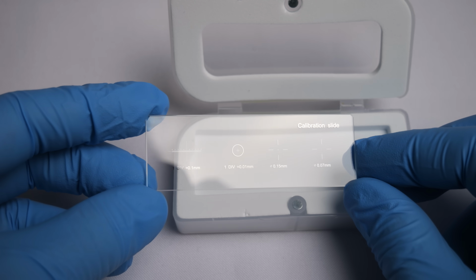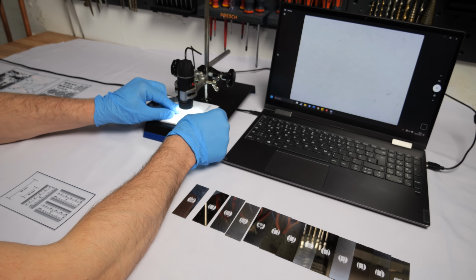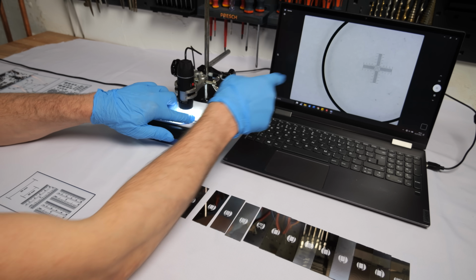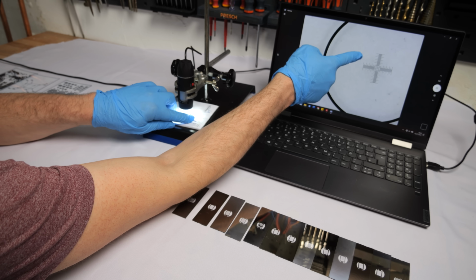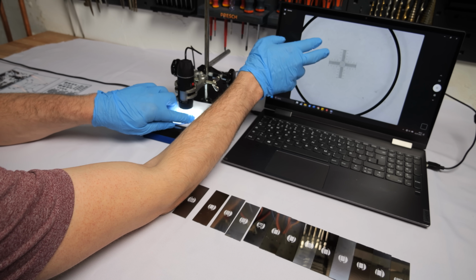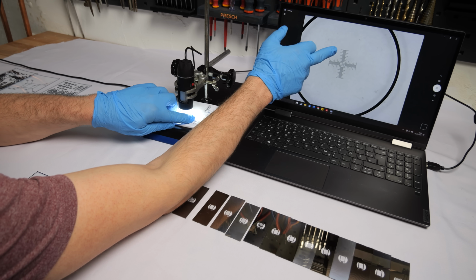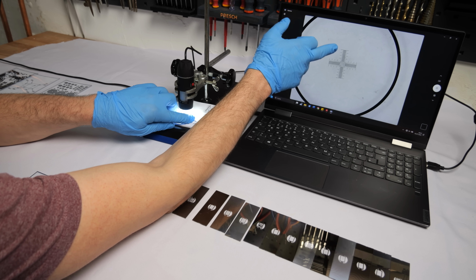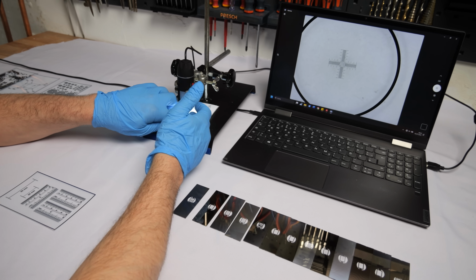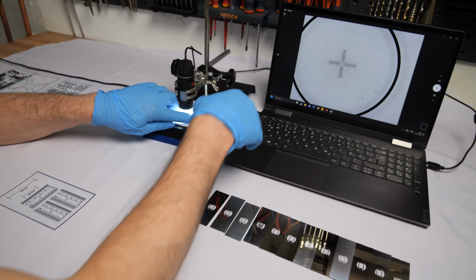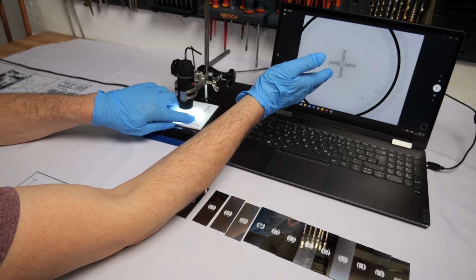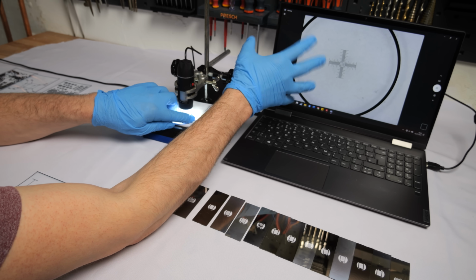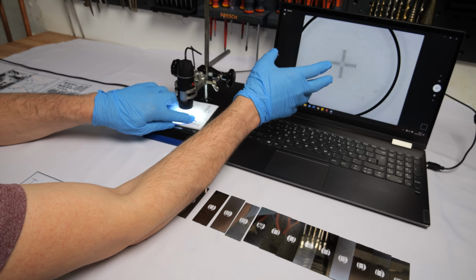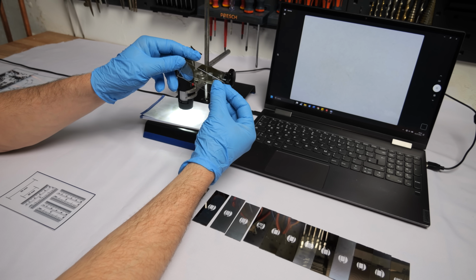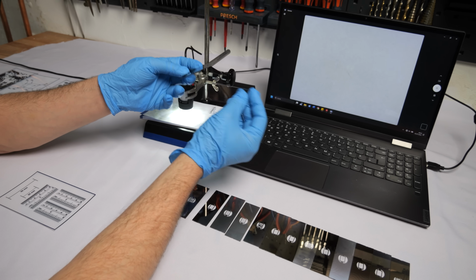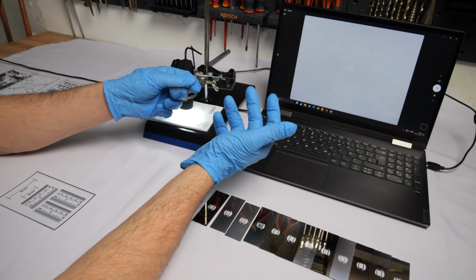To measure those distances, I'm using a calibration slide, and my microscope is actually not able to see the smallest division here, which is 0.01 millimeters, but that doesn't matter. I just took a screenshot of this picture here and measured the pixels from the divisions I could see, which is 0.05 millimeters. And then with the same magnification, I took screenshots of all the other structures and measured the pixels there. And this way I could determine that I'm having a feature size of approximately 20 micrometers, some even a little bit smaller. I didn't want to place the calibration slide on top or below the titanium structures, because this way, due to perspective, one of them would of course appear larger.